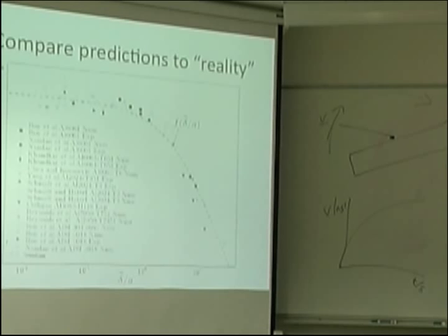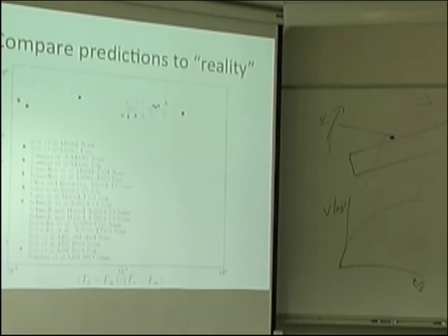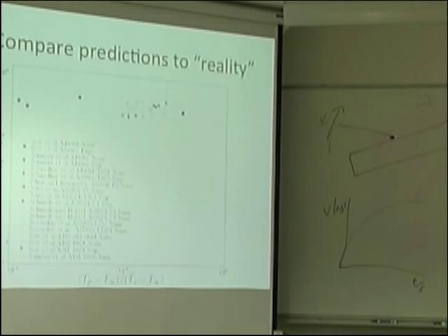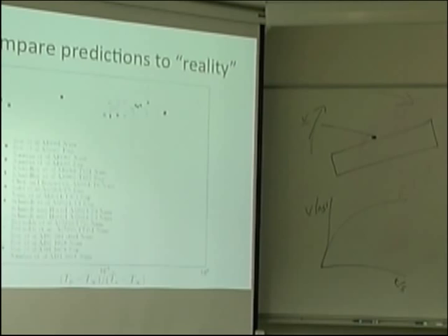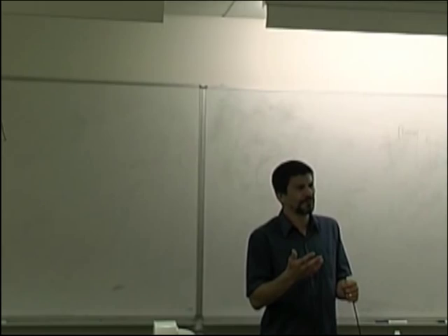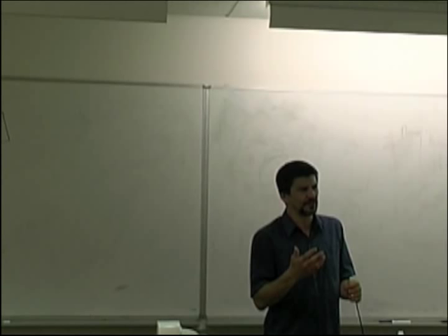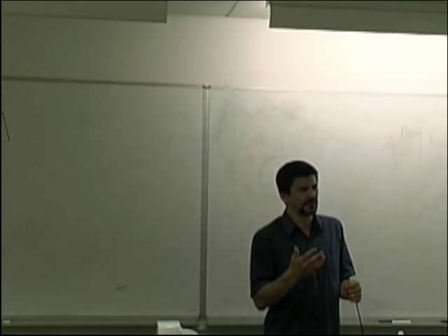At this stage, at least some of you might be wondering, what a cheater. Because it's true that I more or less got the right order of magnitude. But if I had expanded my scale here, this would be a cloud. How could you say I have any meaningful prediction? Because it's pretty interesting that I picked this large scale for the graph. When in reality my variation is just that. But if I'm a cheater, it's not because of this. Because here I have another graph in which I assume that the shear layer is thin. Right? And the shear layer, so when I'm moving in that direction, it is thin. When I'm moving in that direction, it's thick. So in this area, I should be good. And actually, I am more or less good. Right? I'm 0.8 from reality. And as I depart, as my hypothesis is weaker and weaker, here I'm predicting that the shear layer is 10 times thicker than the pin. It's not true. I'm predicting that, but I'm outside my model. And look at this. Right? It started to depart. And I captured that. And I captured that with a pretty good variation.